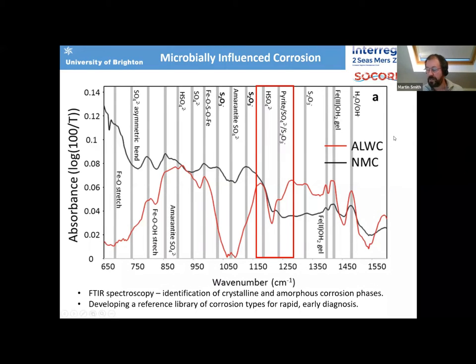And where we've tried to differentiate normal marine corrosion and accelerated low water corrosion at Shoreham as part of the MAPAMIC project, it's quite clear we've got sulfur species present in both corrosion types. So we have the precursor generation of sulfate minerals in what appears to be normal marine corrosion, where we've got small pockets of anoxia that allow the initial colonization, potentially by sulfate-reducing bacteria, that then develop into the major problem, accelerated low water corrosion blisters.